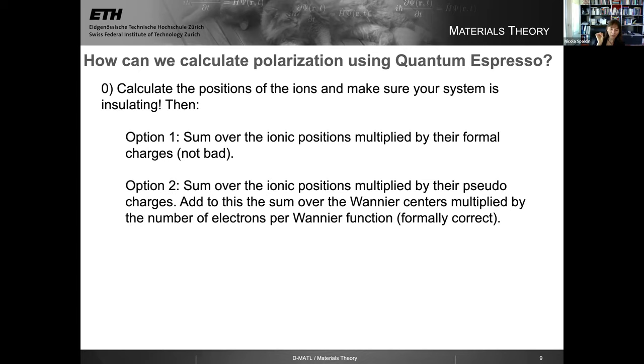If you want to get formally the correct answer, you can do one of two options. The second option, you would first sum over the ionic positions again and multiply by the pseudo charges, the charges on the pseudo potentials. And that gives you the polarization, the dipole moment per unit cell coming from the ions described by the pseudo potentials. Then, of course, you have to add to this the contribution from your valence electrons. And you can calculate that by summing over the centers of the Wannier functions, the Wannier centers, multiplied by however many electrons each Wannier function takes, usually two or maybe one if it's a magnetic system. And this approach is formally correct. This gives you formally the correct DFT value for the polarization.